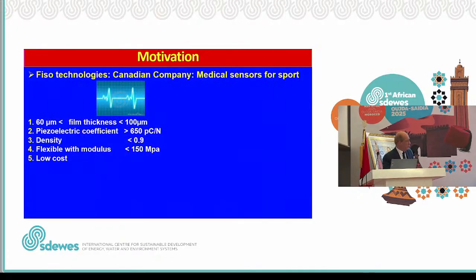So at that time, we had the following requests from the Canadian company. They asked us to produce a film which is very thin, with a thickness between 60 to 100 microns, and a piezoelectric coefficient which is very high, because the heartbeats do not generate very high stress, just small stress or small deformation. So you have to be able to transform this small deformation into a signal. So we need a highly piezoelectric material.